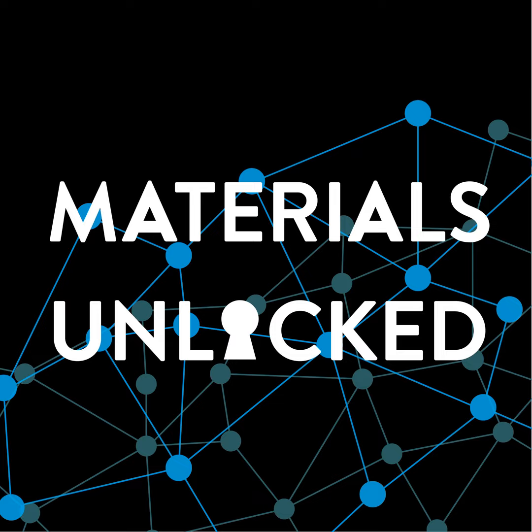For 3D printing, we take that same billet and we melt it, but now what we need to do is put a lot of argon in. And argon is reasonably abundant, but it requires its own manufacturing process to get to it. And the reason we need that argon is that the majority of the powders we use are gas atomized. So what this means is we've melted our alloy and we pour it into a flowing stream of argon. And we use argon because it doesn't react with the alloy. So we're not changing our composition. We're not putting in weird oxides or anything like that. And the argon literally blows this stream of molten metal apart, and we end up with a fine powder.